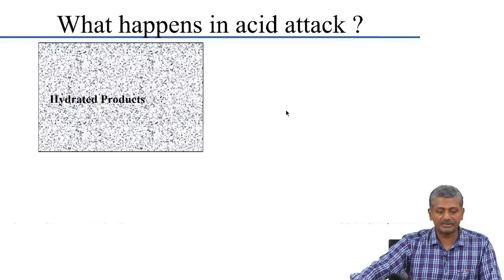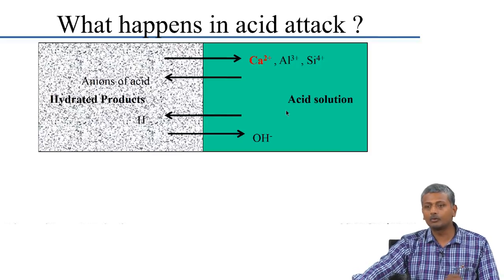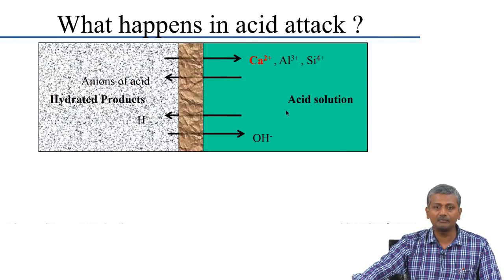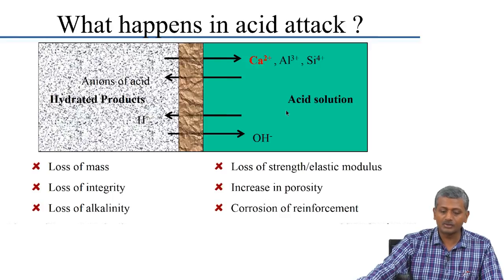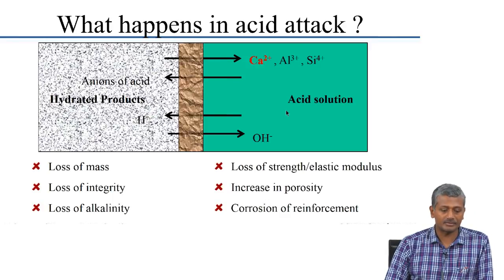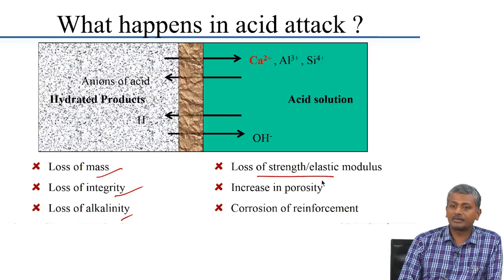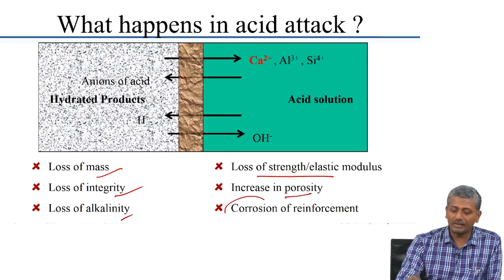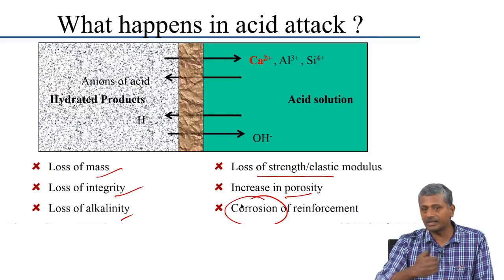What happens in acid attack is loss of mass, loss of integrity, and loss of alkalinity, resulting in reduction of strength and elastic modulus, increase in porosity, and finally because pH reduction can reach the level of reinforcing steel, acid attack generally gives rise to corrosion of reinforcement. More specifically in concrete sewers: sewage carried in the lower half of the pipe contains anaerobic bacteria or sulphate-reducing bacteria that generate hydrogen sulphide gas. This gas rises to the top, condenses, and is acted upon by sulphur-oxidising aerobic bacteria that generate sulphuric acid on the outer crown of the pipe. The submerged portion of the pipe may be free from damage while the crown suffers.